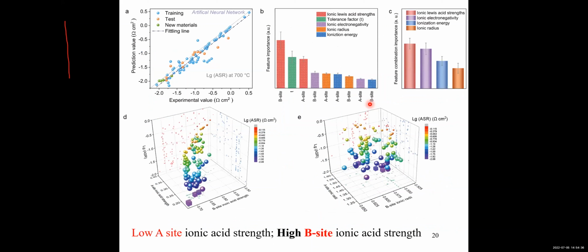Recently we developed this approach looking at a few descriptors such as the ionic Lewis acid strength, tolerance factor, and so on, because these descriptors are widely used in the literature for material selection. We first look at whether these descriptors are important in terms of the area specific resistance of the material, and found that ionic Lewis acid strength shows the highest importance.